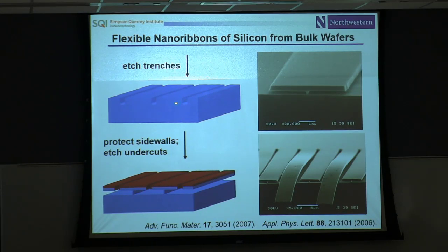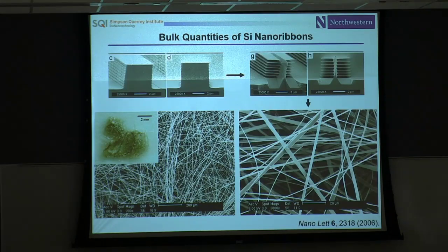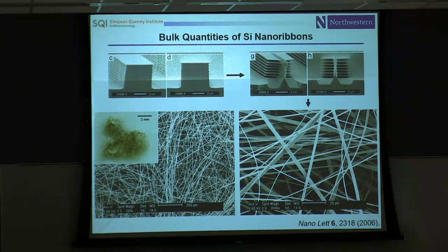There are anisotropic etching tricks that allow you to take a wafer and shave off very thin nanoscale ribbons of device-grade monocrystalline silicon from the near-surface region. This is KOH etching of a silicon wafer with a 1-1-1 orientation. You can sculpt the sidewalls, evaporate directional flux metal as a resist layer on the sidewalls leaving certain regions of silicon exposed, dunk that into a KOH or TMAH etchant, and create bulk quantities of silicon nanoribbons in a single process sequence.